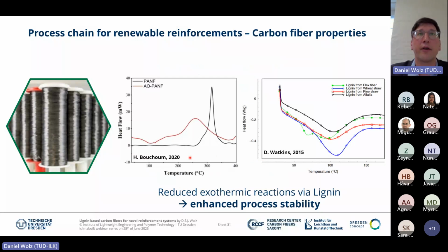So if we look here at a polyacrylonitrile precursor fiber in the heat convection oven, we see a very broad and very strong and clear peak. Meaning in process regulation, we have the challenge to avoid overheating and therefore fiber break, as this would mean a complete loss of the precursor fiber. There are possibilities to broaden this by additives like hydroxides, methacryl or vinyl compounds.